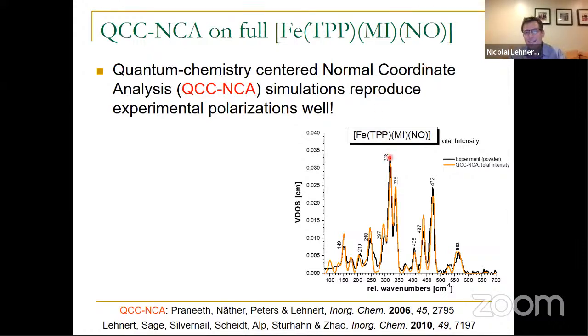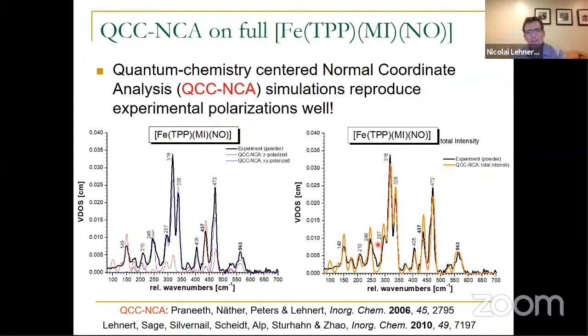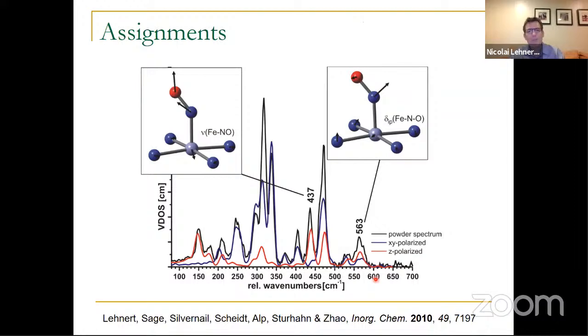So the spectrum in black is the experimental spectrum, and the one in orange is the simulation. And then in the simulation, we can also look at the polarizations, and you can see that we can reproduce in the simulation the fact that the 437 mode is strongly out-of-plane polarized, and the 563 has this kind of mixed polarization, right? So we're able to reproduce these key features of the spectrum in our simulation. So that means we can now make our assignment, right? We assign the 437 wave number feature to the Fe-NO stretch, and this one to the bending mode.